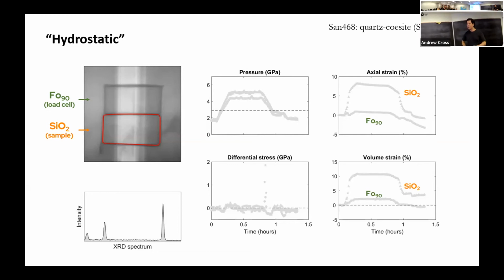One of the key things that we're doing with these experiments, I said that normally we'd have opaque anvils on the right-hand side because we only really care about measuring the shortening in the sample. In this case, we're swapping them out and using all four diamonds, so the whole sample is X-ray transparent. And we're able to measure not only changes in length, but changes in width, and from there, get changes in volume. The only reason that we don't use four diamonds as routine is they're about $700 a pop, so if you break them, it can rack up quite quickly.